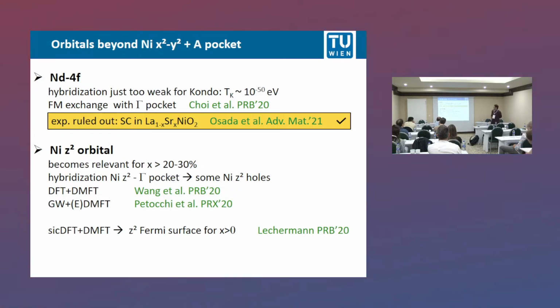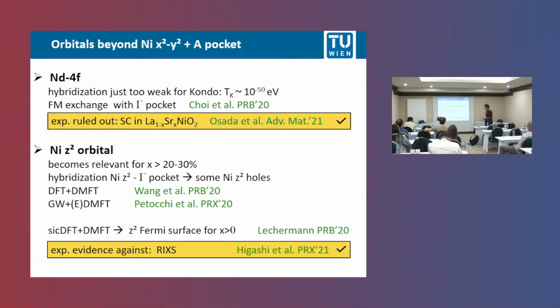And there's a second theory by Frank Lechermann, and as he nicely showed, the difference comes about just by using DFT plus something instead of density functional theory. And there you get rid of this A pocket, and instead this z squared Fermi surface is present for any doping of the system. That is similar as in our calculation for larger doping. We get similar physics, but only for 25 or 30% doping. Okay, that is what I wanted to say about the modeling and arriving at this one-band description.